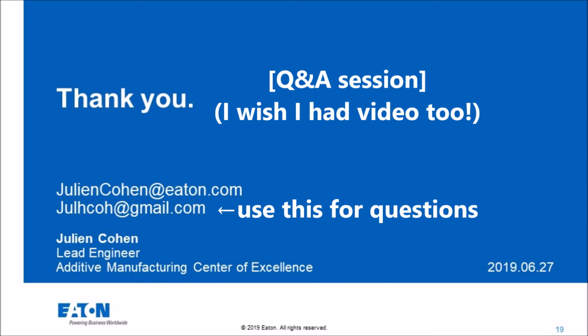So to your point, Eaton has done a fairly extensive amount of work in terms of material characterization and understanding what we're getting out of our process. We have what we term a qualified metallurgical process, which is the combination of the material, so the powder feedstock, the parameter set, which is all of the laser parameters and machine parameters, so basically everything that goes into creating the part, and for a specific application. What you can allow for a specific application is not going to be the same as for another. So, to your point, I don't have a really good answer. It is very difficult to define, and from my perspective, is it possible to create more general specifications? Can you make an aluminum, silicon, magnesium specification for rotating parts? I hope so is the answer, but right now I'm not sure.